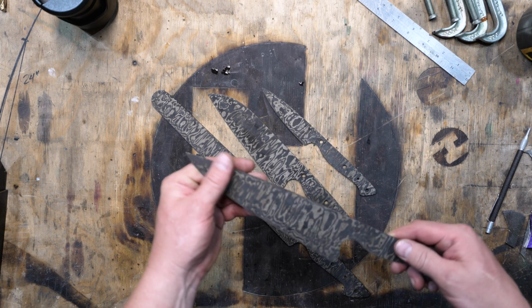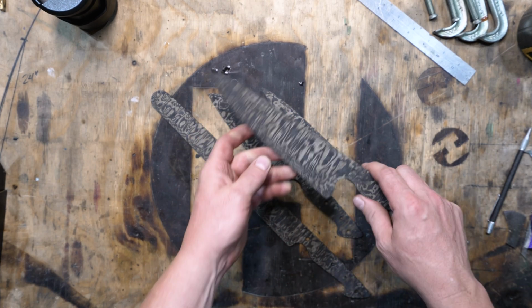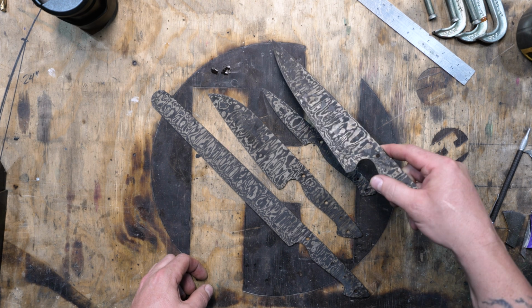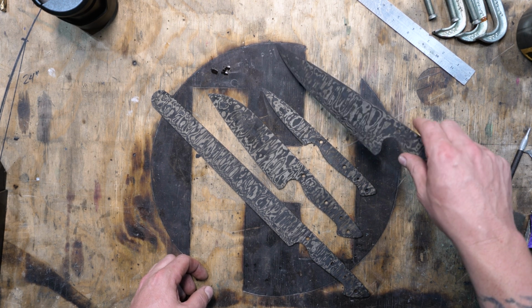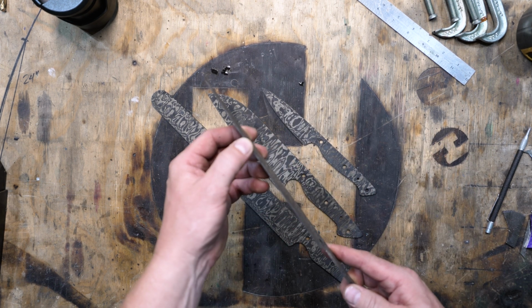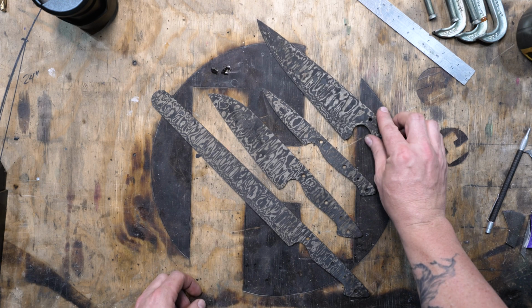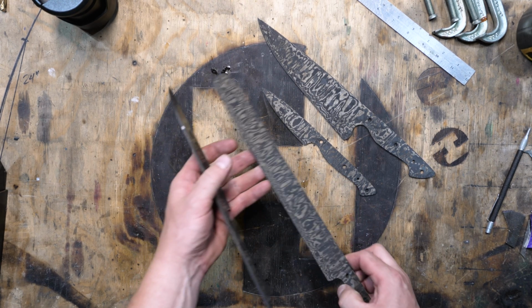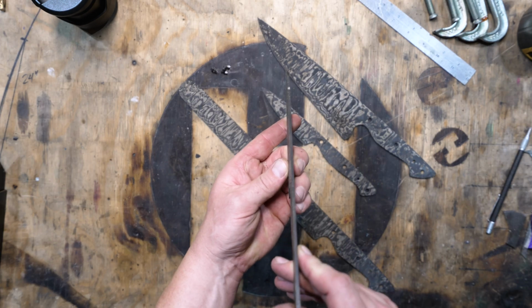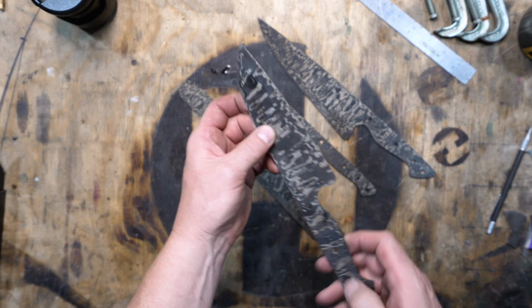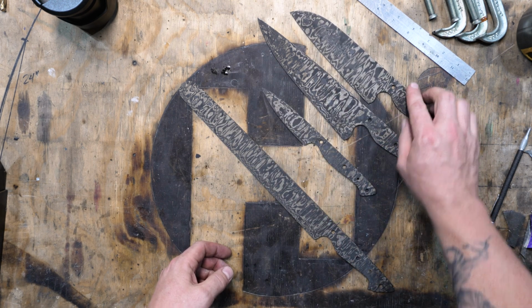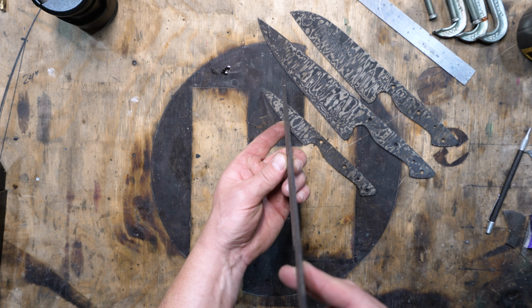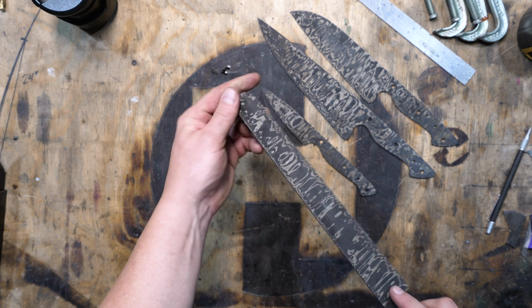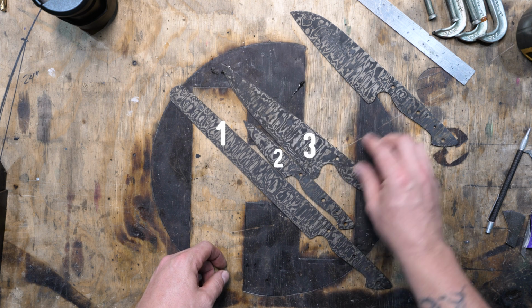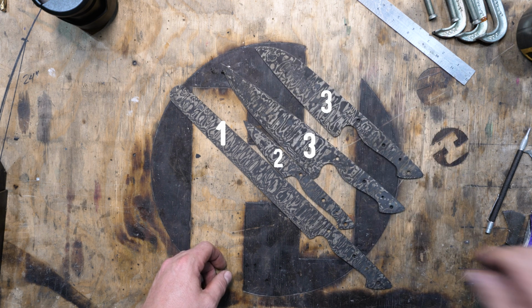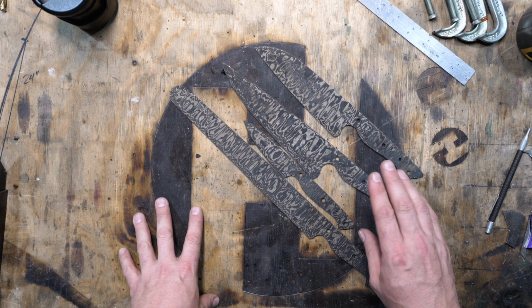So here are the knives. In case I forgot to tell you, my temper cycle for my cutlery is 2 cycles at 2 hours and 350 degrees. That usually makes for a nice hardness for this cutlery. So the 2 that were warped, the Santoku, the warp came out almost all the way, but well enough in grinding range. So that's going to be good. And then the brisket knife, the warp came all the way out. So we've got 3 perfectly heat treated knives. That's going to be it for these as far as heat treat goes.